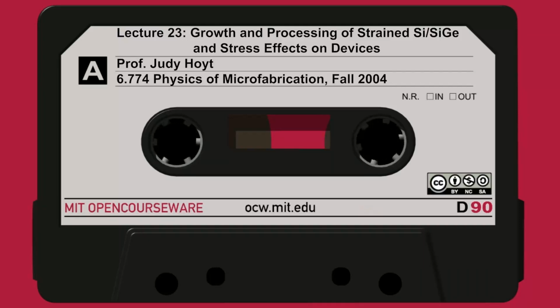basically. Because it looks something like this. It's a 1/2 micron long, but it goes a micron into the board, into the page. So this is 0.5, and this is 1. So by definition, that's 1/2 a square. Because if it were a full square, there'd be 2 of these right next to each other. So then you can just get the resistance of the silicide to be 3.8 ohms per square times a 1/2 a square.